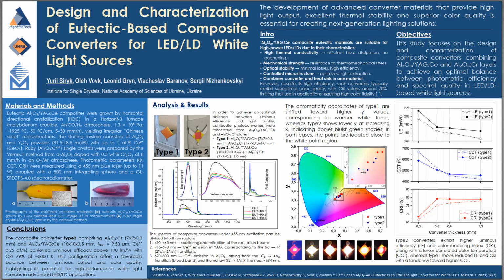Type 2 converters exhibit a higher luminous efficiency and color rendering index, with slightly lower correlated color temperature, compared to Type 1. For instance, the Type 2 converter configuration with 0.3 mm ruby and 0.3 mm eutectic plate provides luminous efficiency about 170 lumens per watt, color rendering index around 79, and correlated color temperature near 6000 Kelvin.